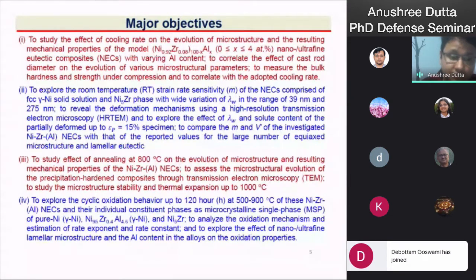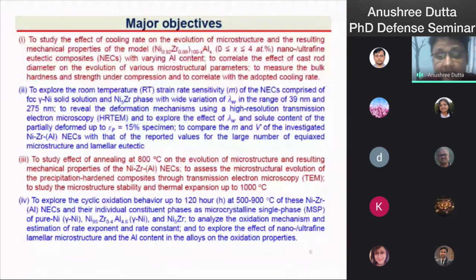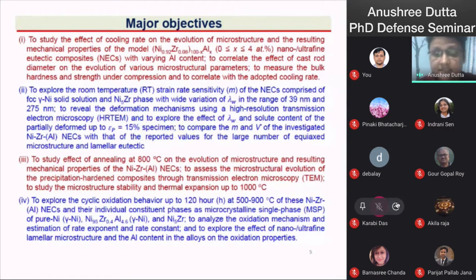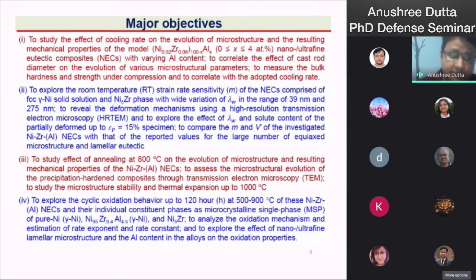The third objective is to study the effect of annealing at 800 degrees centigrade on the evolution of microstructure and resulting mechanical properties of nickel-zirconium-aluminum NEC, to assess the microstructural evolution and precipitation-hardened composite through transmission electron microscopy, and to study the thermal stability and microstructure stability at high temperature up to 1000 degrees centigrade.